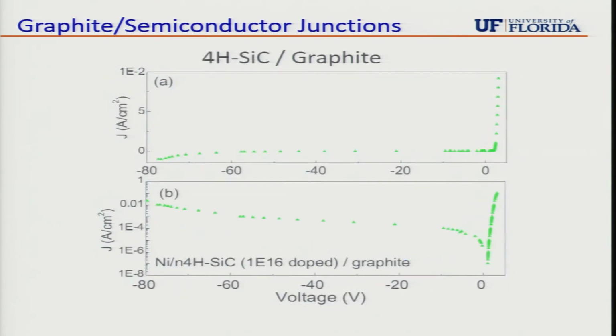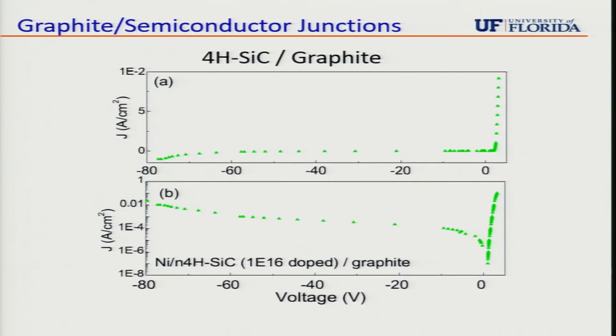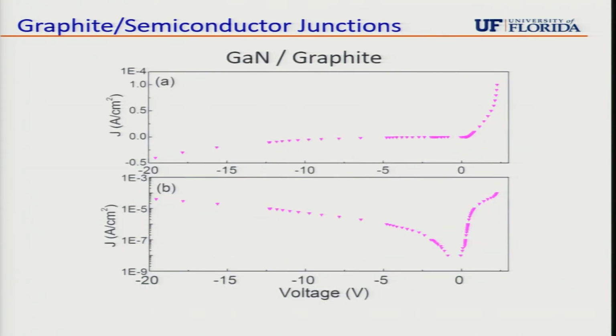So it works for the silicon carbide polytype on graphite, and it works for gallium nitride. So it looked like a pretty universal technique for at least graphite on the semiconductors. And you'll see as I go through this talk that we've tried many different Van der Waals crystals with a similar technique. So it looked to us like we needed to learn a lot more about Schottky barriers and how they behave at low temperatures, because we want to study these phenomena at low temperatures.